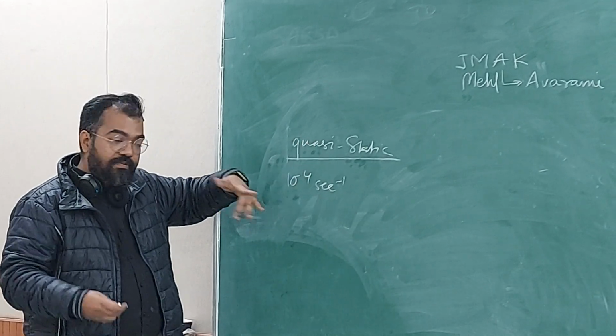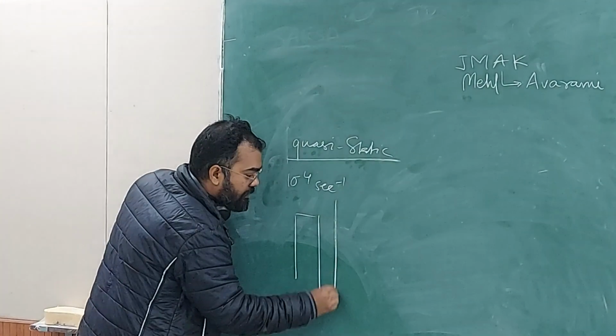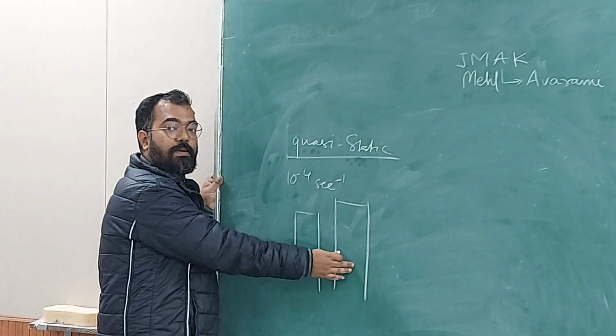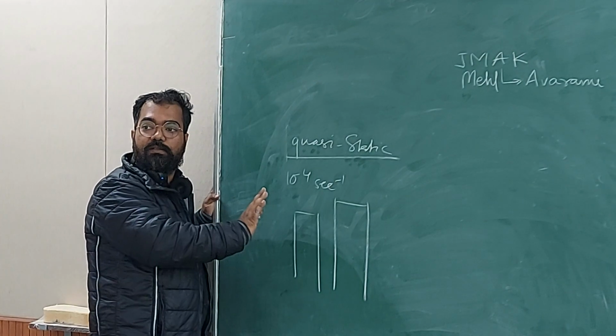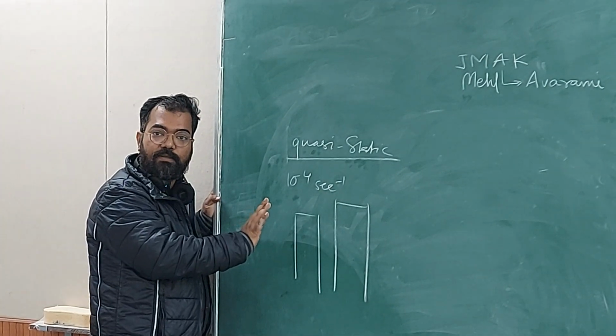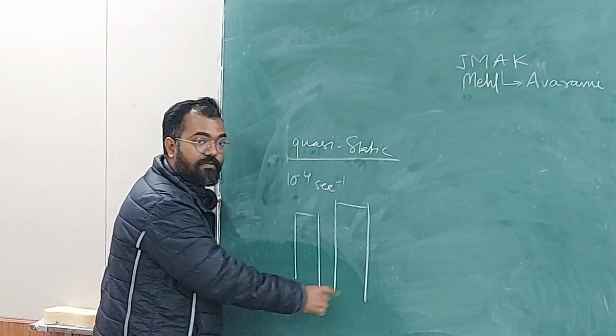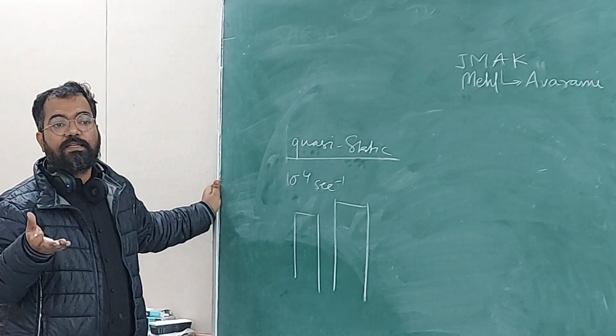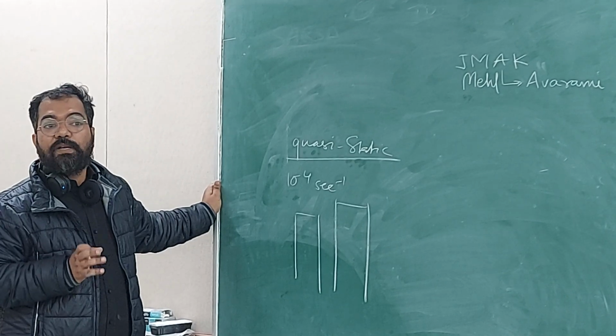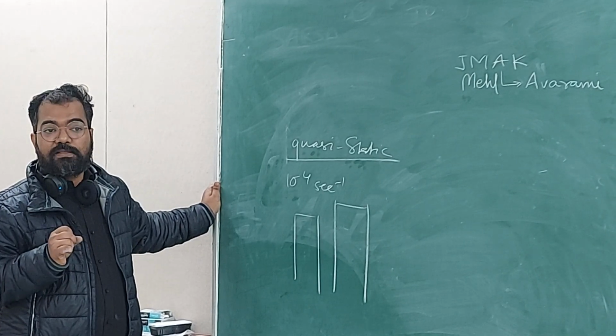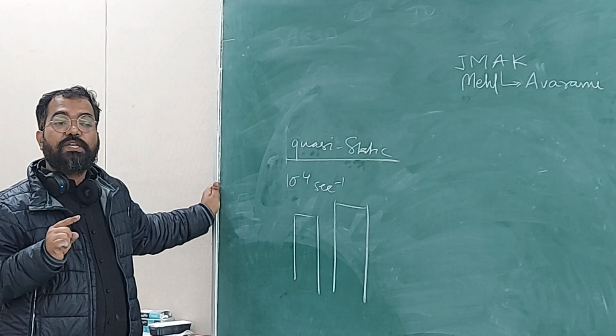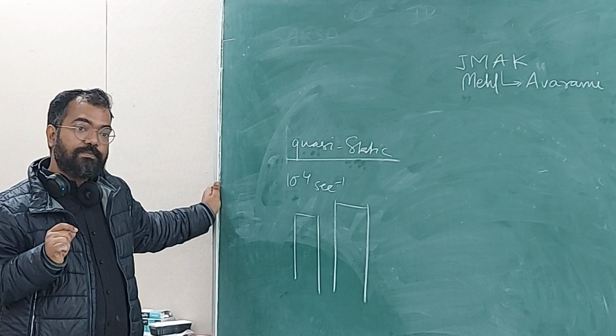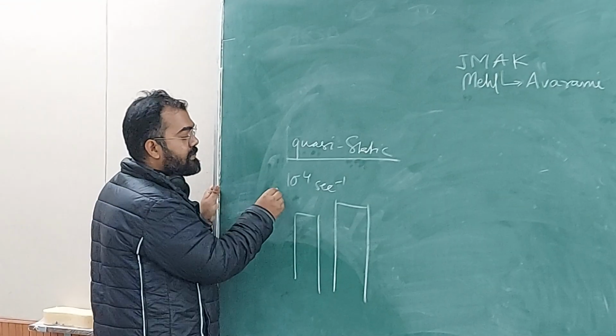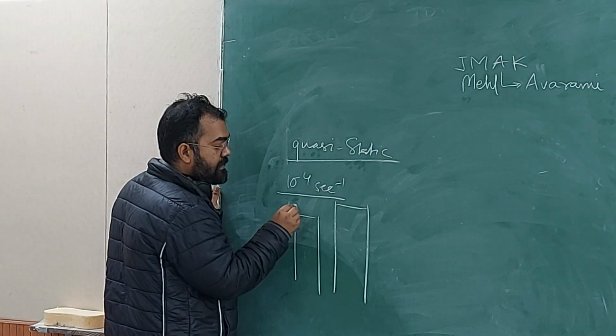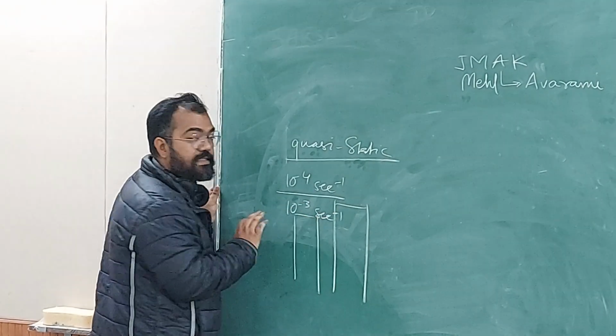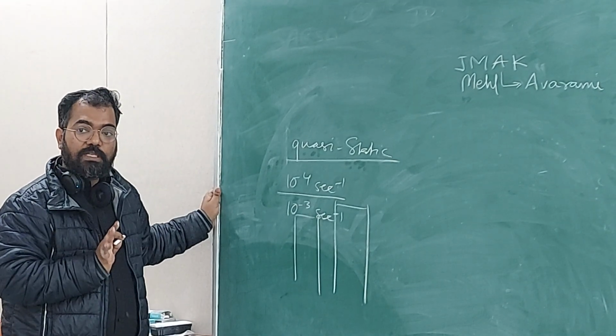Almost as if at every step, a tensile sample elongated at both ends as if there has been no movement in the material. So every point you can take as the reference configuration. Every point you can take as t is equal to 0. Okay, so metallic materials do not show strain rate dependence for a strain rate change of the order of 1000 at least. Okay, so if you do a tensile test at 10 to the power minus 4 per second, and then you do a tensile test at 10 to the power minus 3 per second, you will not see any change in the stress strain diagram. Nothing.